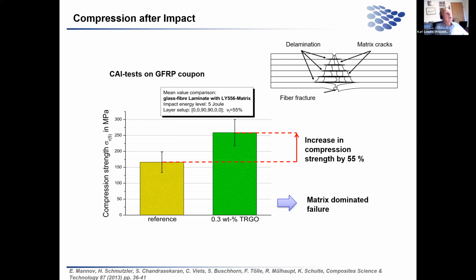If we now make a compression after impact test with composite materials, in this case glass fiber - we have tests elsewhere showing similar results with carbon fibers - then if we just have a neat resin as matrix, we have this amount. We have an increase in compression after impact strength of about 55% if we have, in this case, thermally reduced graphite oxide in the matrix instead of neat resin. This is a tremendous increase.